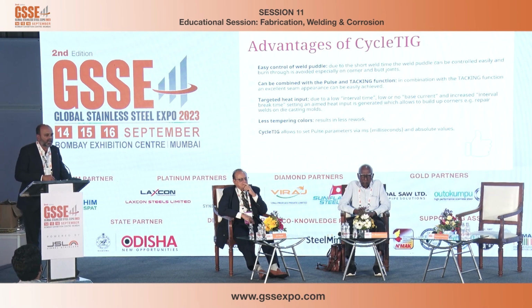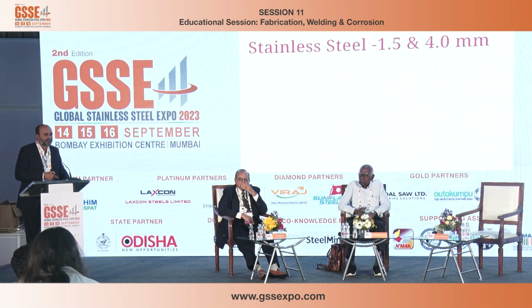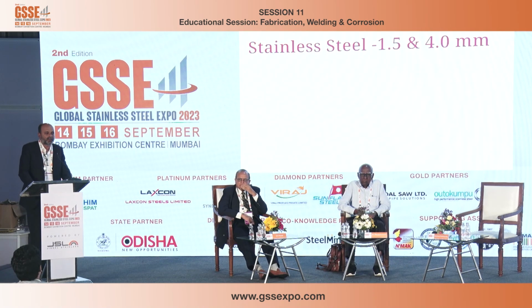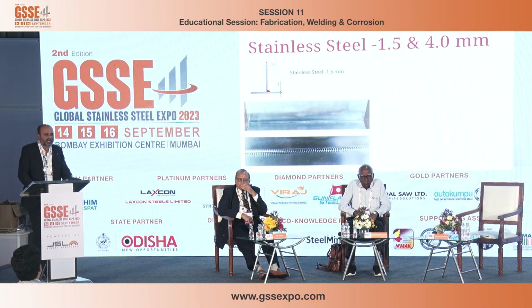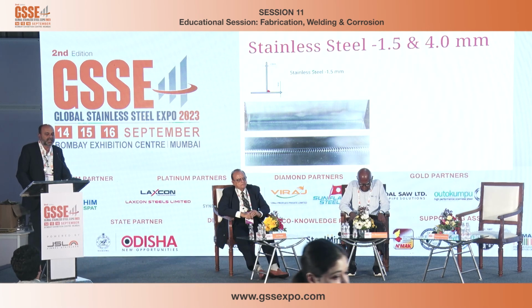So with cycle TIG, I would like to show you how it looks when it is used in stainless steel. Here I take an example of a 1.5 mm thick material and a 4 mm thick material, where you can see the look and feel of cycle TIG when I weld a 1.5 mm fillet weld. I don't know how many of you are from the welding field, but this joint is called a fillet joint, where you will be able to weld even a 1.5 mm thickness without any change in the color of the weld seam. So you can understand one thing, the heat affected zone is very, very controlled.